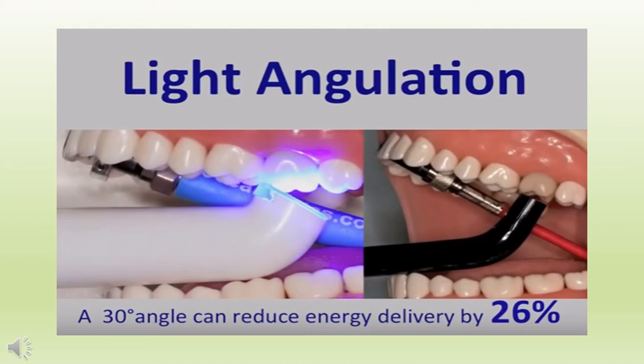Angulation of the curing tip is another variable. It should be parallel to the restoration surface to achieve maximum light intensity. The area of the cure is circular when the tip of the unit is held perpendicular, otherwise it is elliptical. So, energy is spread over a greater area, which reduces its intensity.